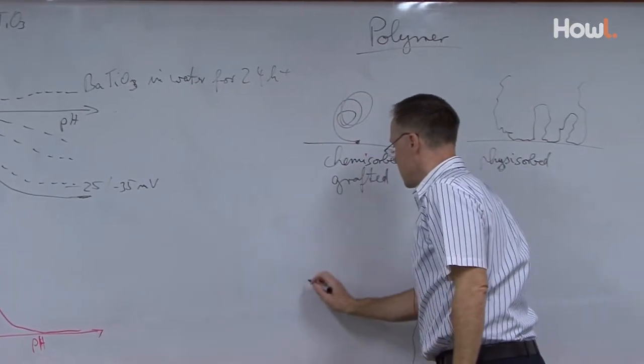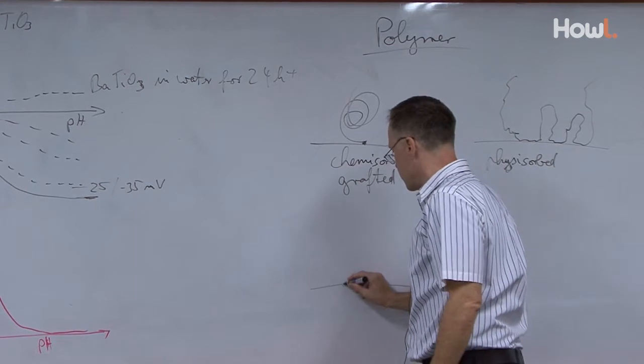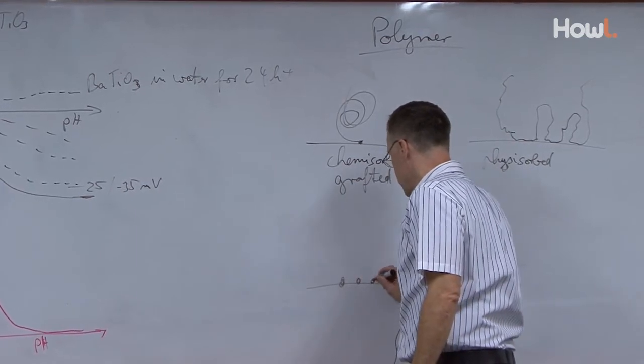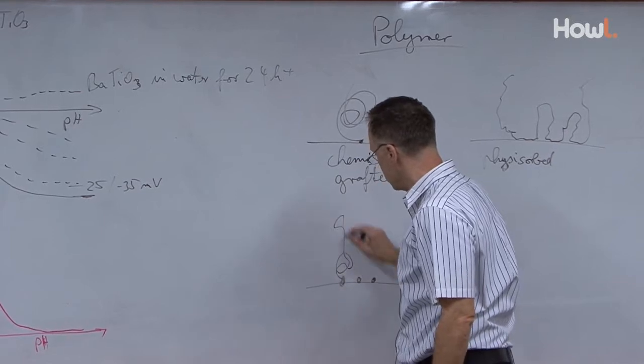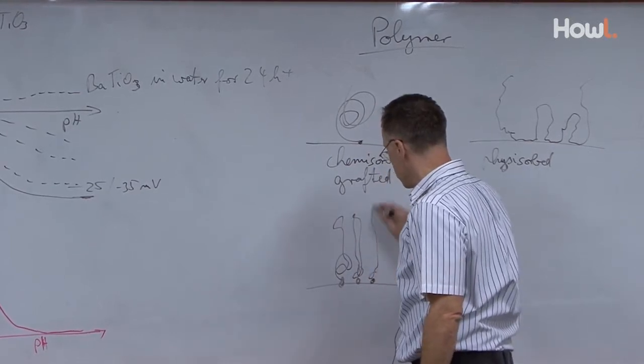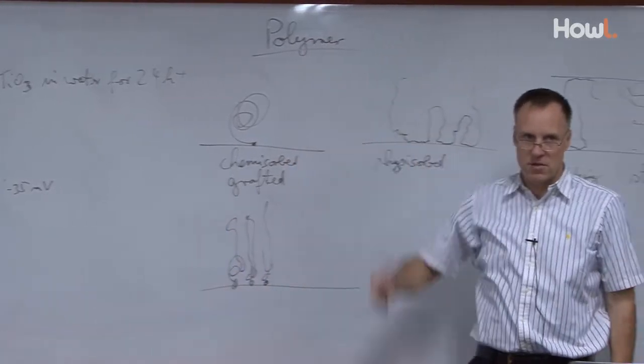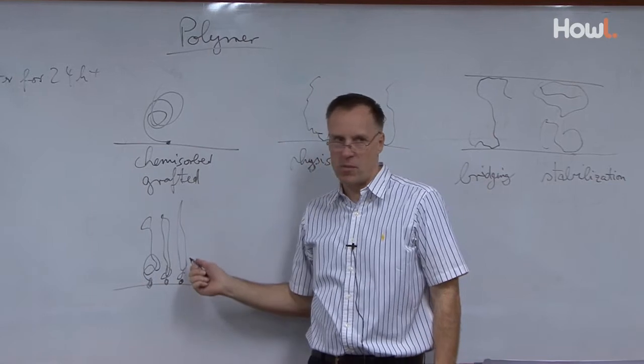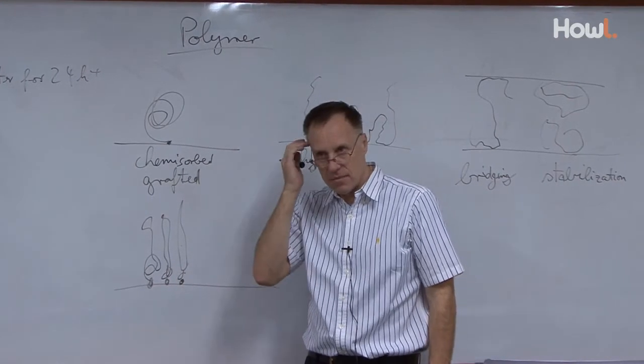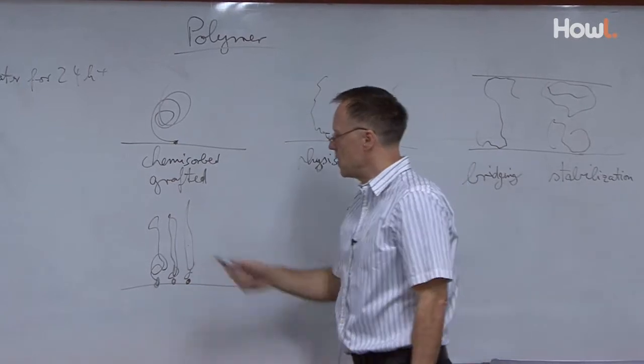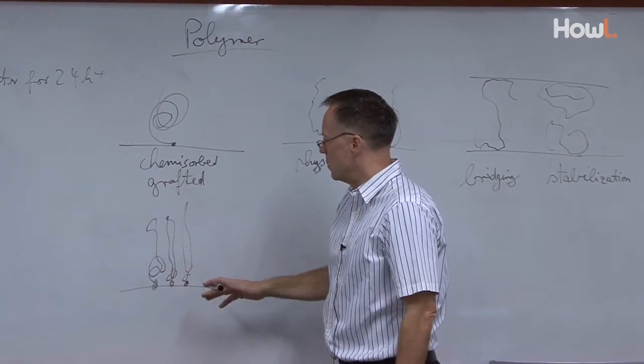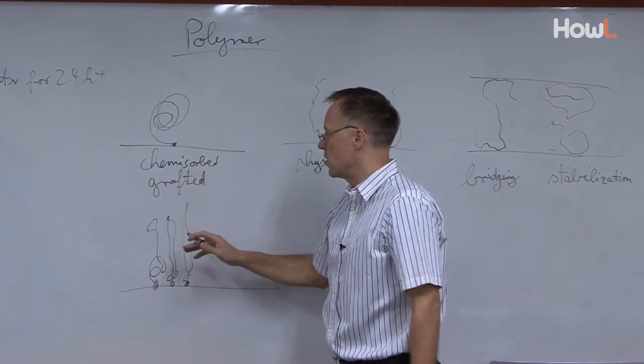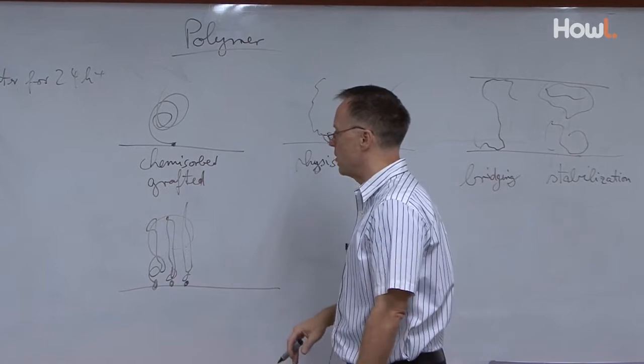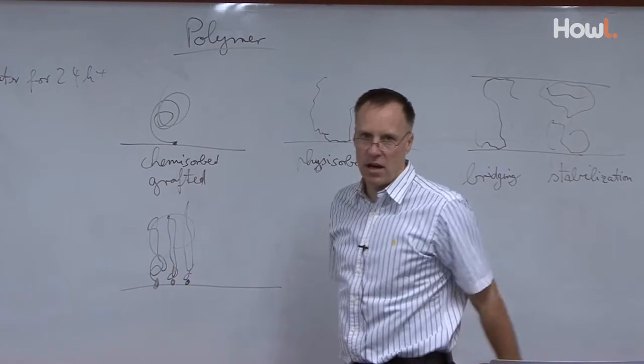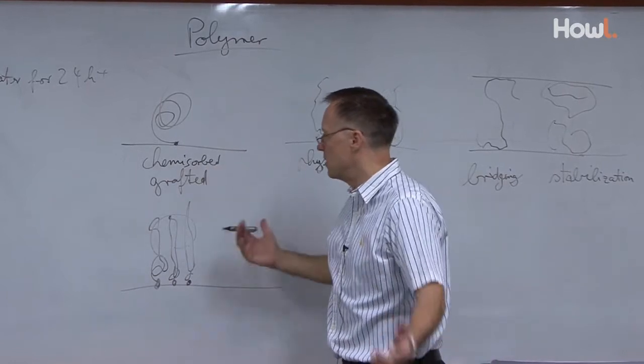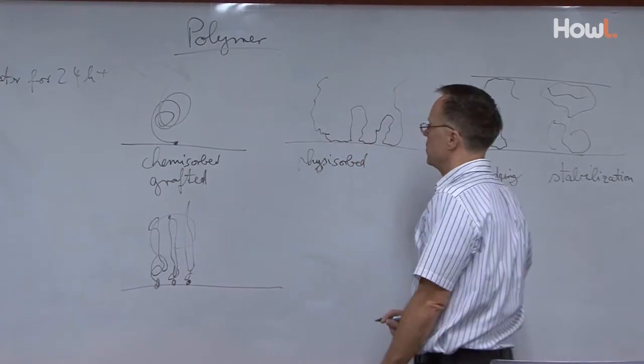So what you like to do is then you form a surface where you chemigraft really strongly at a lot of dense anchor points, polymers, and because the next one is grafted here, you see now the coils are deformed into long stretches. And this is an entropically unfavorable state because you have lack of freedom for these chains. And by doing so, you now get much stronger repulsion because these chains are in an entropically unfavorable state already, and if they interact with more entropically unfavorable states from the neighboring part, you get the maximum repulsion. So this is the approach that is decent for that.